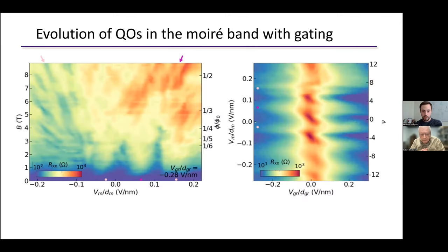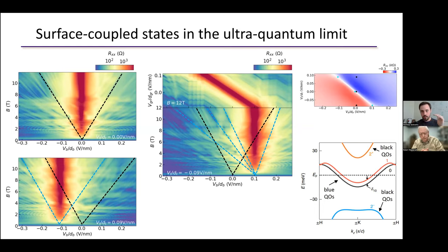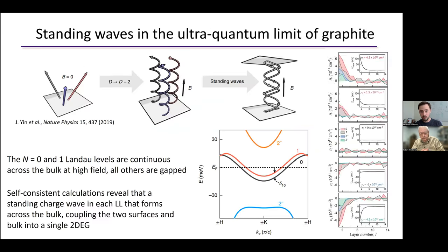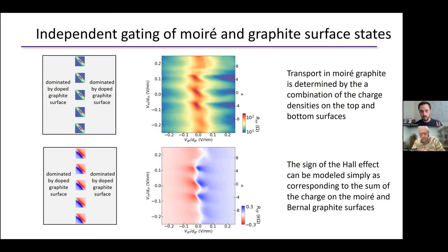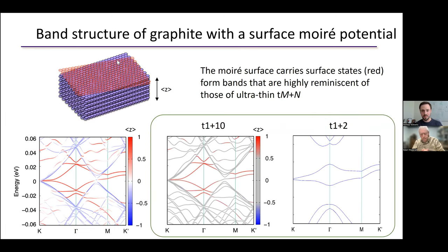Yeah, so we tried that first and it mostly works, but the problem is if you don't consider the hybridization of the twisted bilayer with the rest of the bulk, then you end up with bands that look exactly like twisted bilayer graphene. And twisted bilayer graphene has relatively special bands. Those we don't really want in this system because I think that it's actually too special of a condition for us to be able to really understand what's going on here. But as a zeroth order first pass, what you're saying is exactly correct. You can understand the majority of the physics probably by just thinking of an isolated twisted bilayer coupled to some lightly doped semi-metal. If you really want to get the details right, then you need to consider the tunneling between those two. But you can turn that off in calculation, and what you get is not wildly wrong.